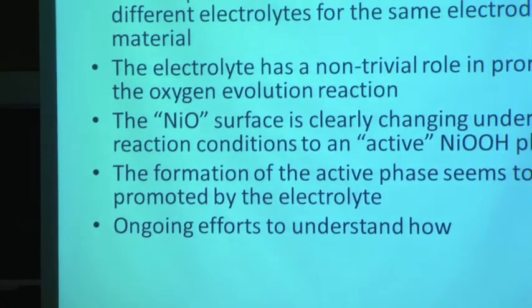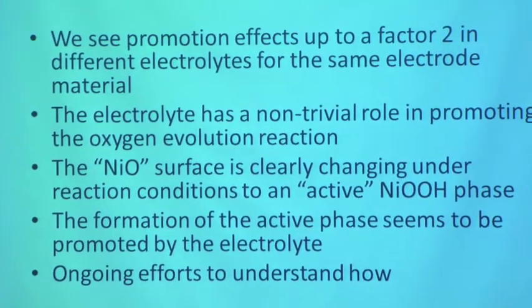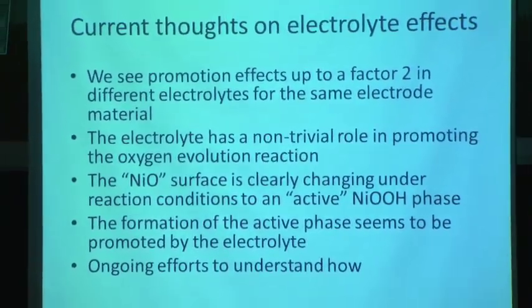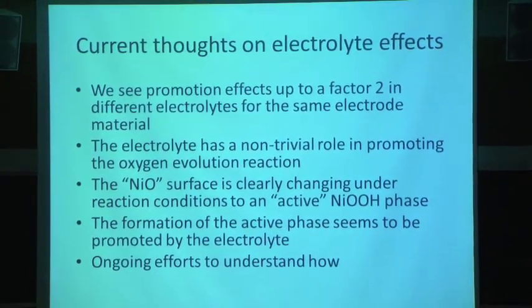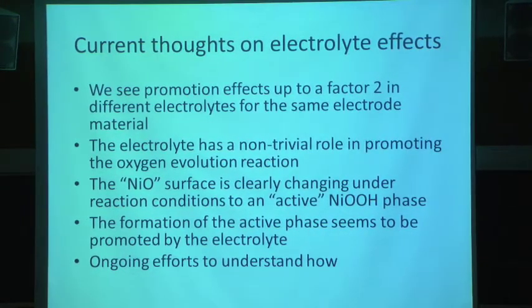So even though we make a very well-defined nickel oxide catalyst in the lab, when we put it into the electrochemical environment, it changes fairly radically. And that active phase may be promoted by the electrolyte. So this is certainly the case for nickel oxide. We have not looked at other oxides to find out how general that idea is.